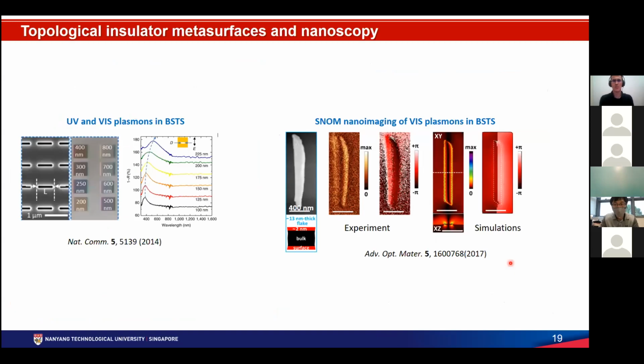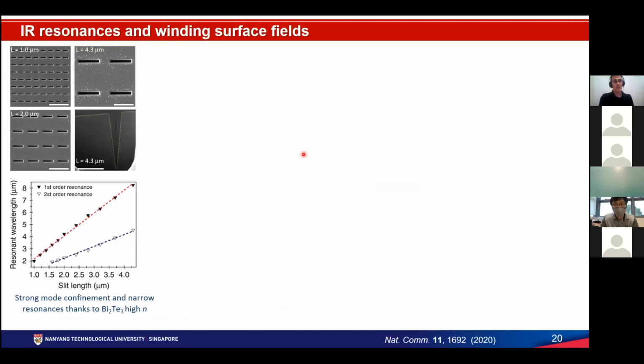We started with the nanostructuring schemes, and we observed that, for example, you can create UV and visible plasmonic resonances in the BSTS, and you can image by a nanoscopy technique like this SNOM the modes that are supported by the structure, either on artificially created discs made with the focused ion beam, or in natural exfoliated flakes that become very small in size, as you can see here in the picture. We also saw that you can follow the resonances all the way from the visible to the infrared, up to almost 10 micron, by changing the slit length.